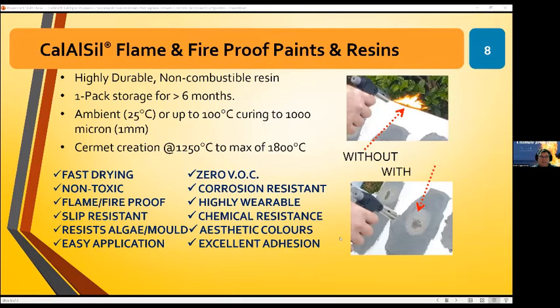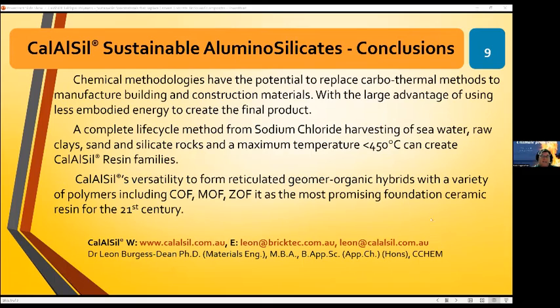As you can see, the particles just really coalesce. Obviously, with chemical resistance, you've got aluminosilicates, very good at chemical resistance. I can make a white paint. I haven't got an image of a white paint here, but they're just more expensive because I can't use fly ash, and no fly ashes are purely white. Essentially, it's just an aluminosilicate with a little bit of borax added to it and a few other components, the calcium hydroxide, for instance. Excellent adhesion. The beauty of the product is the fact that it has excellent adhesion to many things, particularly wood.